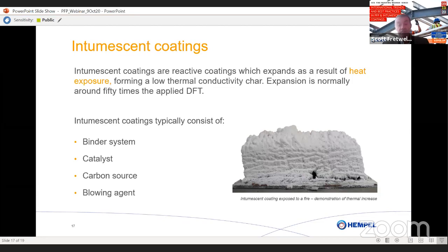Traditionally, intumescent coatings consist of binder, catalyst, carbon source, and blowing agent. And later in my presentation, I will show you a video of the reaction process. As you can see from the image here, the intumescent coating generally expands to around 50 times its original dry film thickness to form that insulation char. So if we apply a millimeter, this char will expand to 50 millimeters, protecting the steelwork.